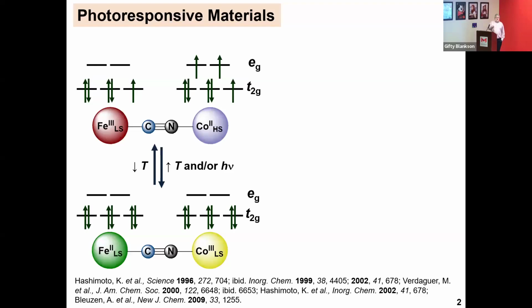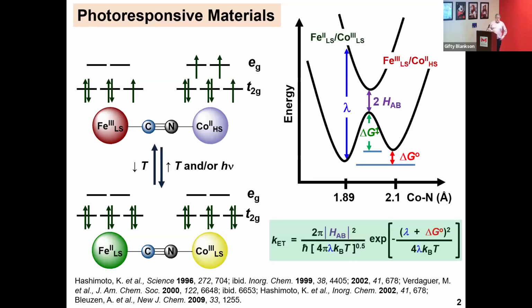And with the spin state change, going from all electrons here to electrons populated here, you have a high spin state, you get a cobalt-2 state. All right, so in other words, to summarize, you're going from 0 unpaired electrons to 4. Right, so the magnetism has to change a lot. And because you're putting electrons in the antibonding orbitals on cobalt, changing the cobalt-nitrogen distances, you're also dramatically changing the color of the material, this metal-cyanide-metal unit.